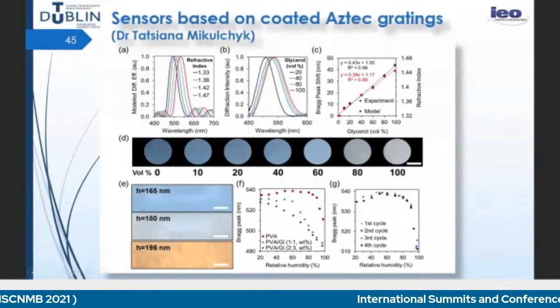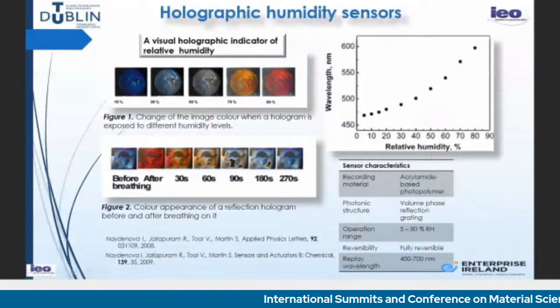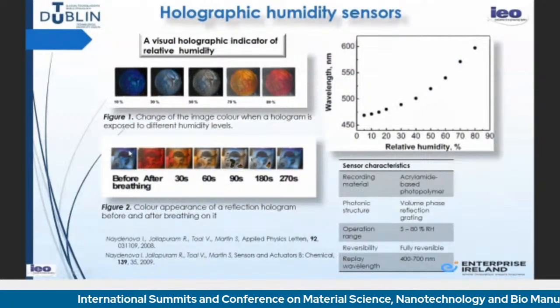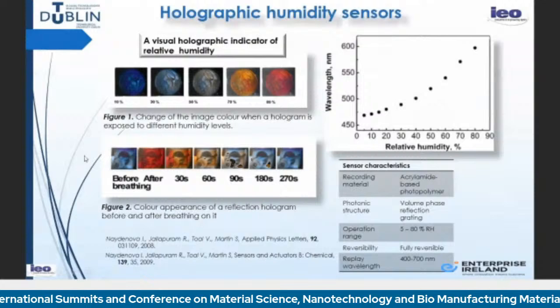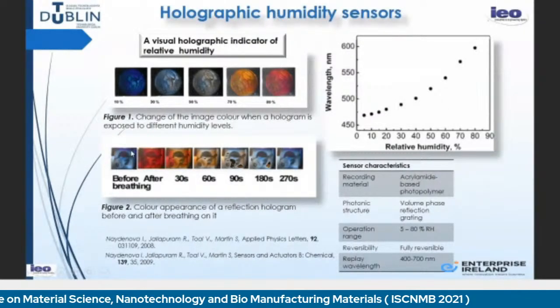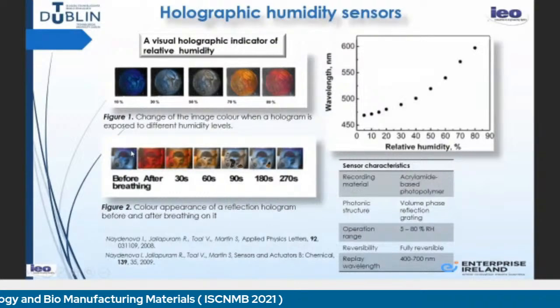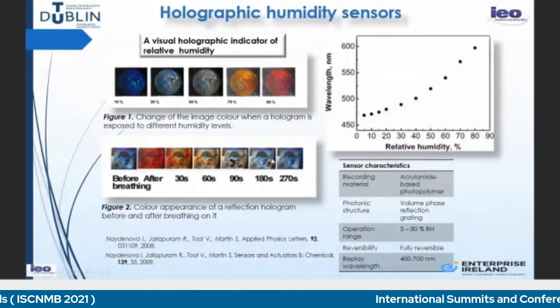For the humidity sensors I already mentioned, all I needed to add here is that we have a composition which is so sensitive that if you breathe on the hologram, in a few seconds it becomes red, and then in 270 seconds it recovers to the original state.